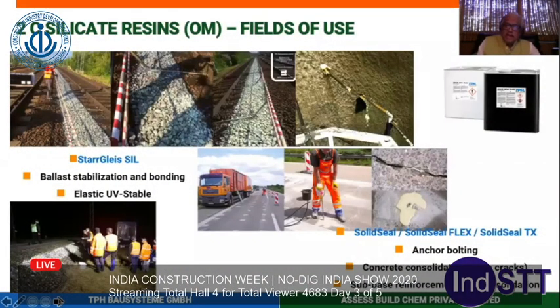Still more versatile resins are the two-component silicate resins. There are also, polyurethane is not the end of the story. There are silicate resins. These are organo-mineral silicate resins. Silicate resins, there are also foaming silicate resins and non-foaming silicate resins. Silicate resins bond very well under wet conditions. Silicate resins, they also foam structurally. Say 1:3, they can be used for the lifting of the structures.